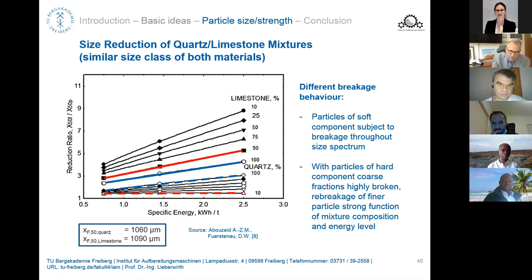The big jump comes if you put just 10% of the quartz into the mixture. So you have a mixture of 10% quartz and 90% limestone. Then all of a sudden the picture changes. With 10% quartz, your quartz curve remains horizontal, which means the quartz is essentially not broken at all. You see no major size reduction, while your limestone curve is getting steeper.